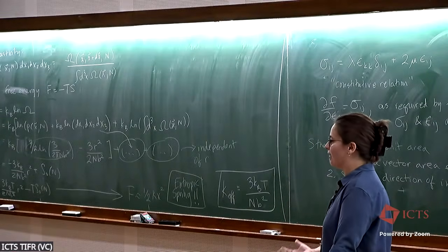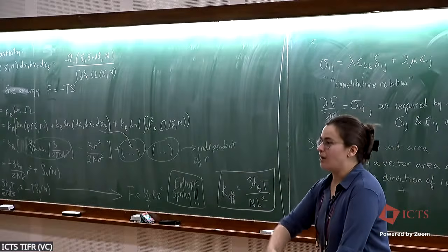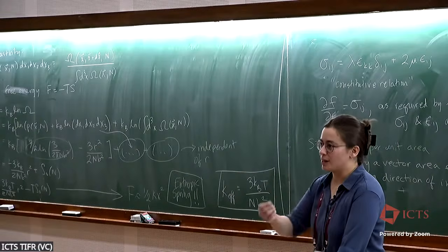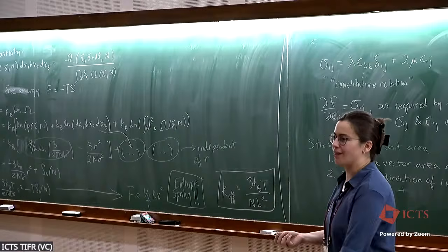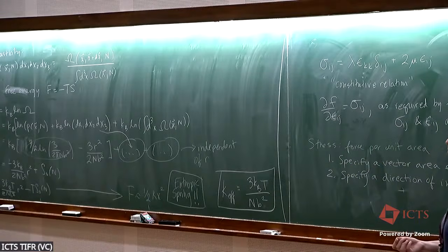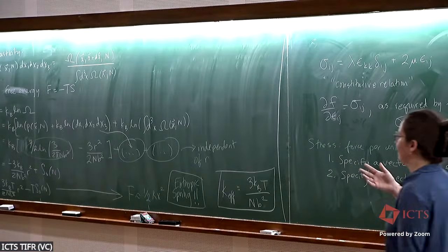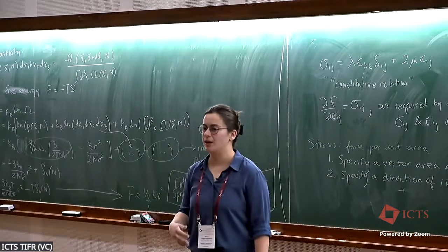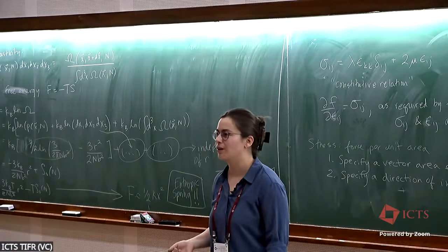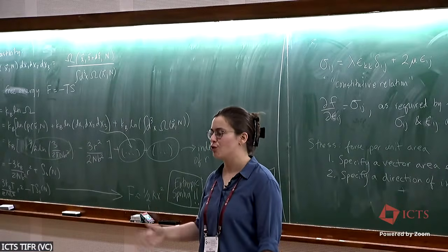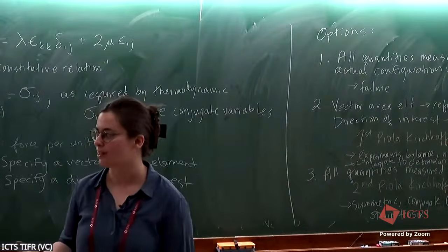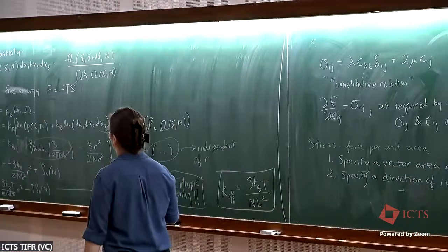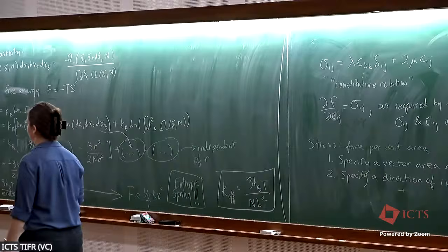In reality, things like entanglements and the fact that the crosslinks themselves also fluctuate, which is left out of the affine network model, all of these things will have big effects on the entropy and therefore big effects on the actual setup itself. But it's a really good starting point for modeling rubber-like elasticity, especially for small to moderate deformations. And I think one way you can think about whether or not these models are reasonable is thinking about the assumptions that go into actually deriving the entropic spring constant of this polymer itself.